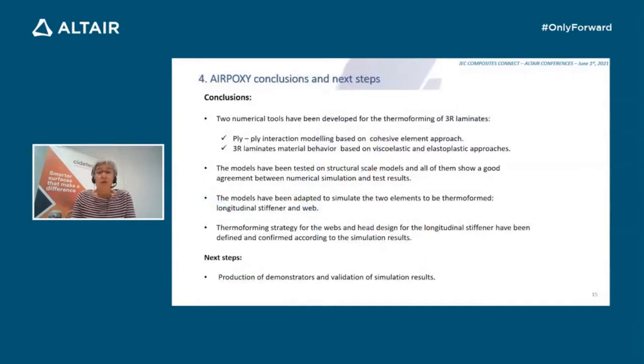Finally, the conclusions. So far, we can conclude that two numerical tools have been developed for the thermoforming of 3R laminates: the ply-ply interaction modeling based on cohesive element approach, and the 3R laminates material behavior based on viscoelastic and elastoplastic approaches. The models have been tested on structural scale models, and all of them show a good agreement between numerical simulation and test results.